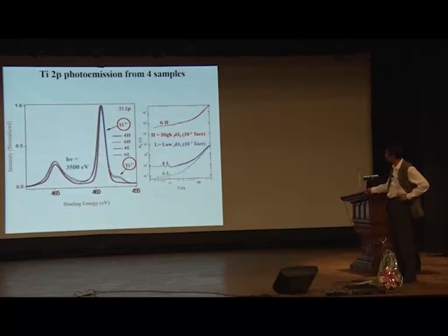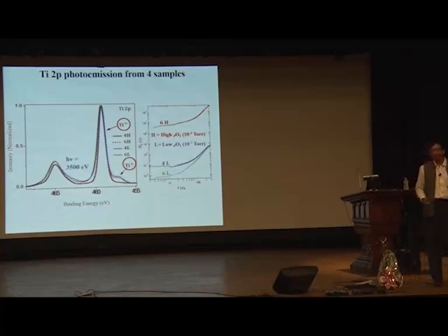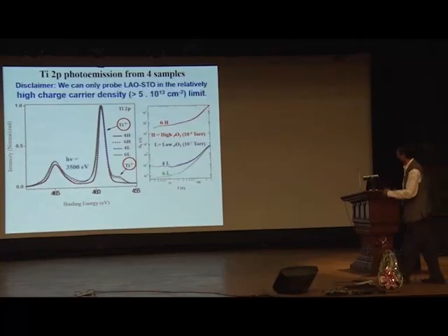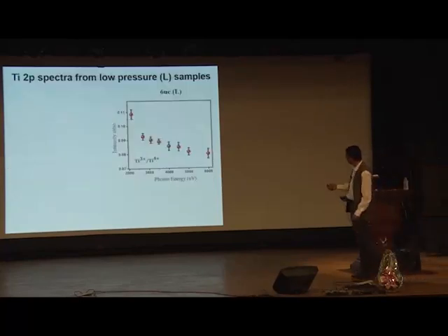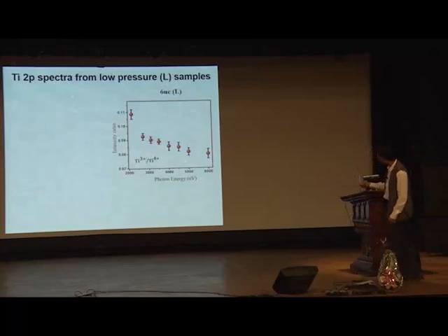These are the material samples that are non-metallic or very weakly metallic. These are more metallic, and you can immediately see where titanium 3+ is energetically. Now, if I look at how this intensity changes, as normalized by that one, as I keep changing my photon energy, I know exactly where titanium 3+ is. And titanium 3+ is where the electrons are, these doped electrons that make it mobile. And that is what we did by looking at the variation of the intensity, and then you have to analyze it, of course.